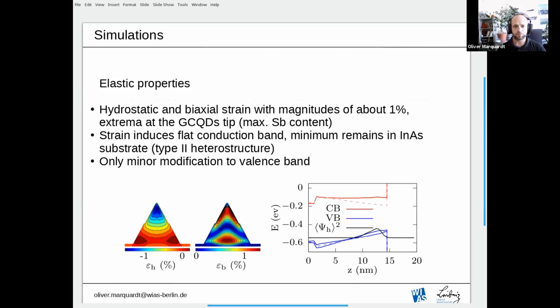So that's the elastic properties. What you see down here is the hydrostatic and the biaxial strain distributions. So magnitudes are about a bit more than 1%, plus and minus here. And not too surprising, the extrema occur here mostly at the tip. It's not too surprising because, first of all, it's a tip, so this is where elastic relaxation happens first. And second, it's the maximum antimony content up there, so of course that's another reason.